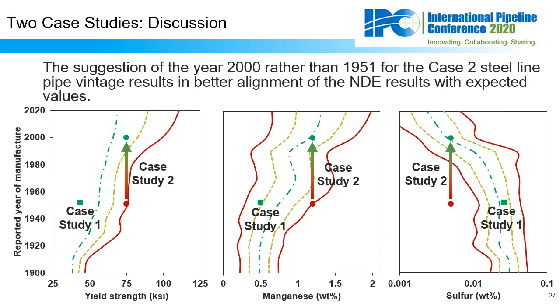And here you see that the suggestion of the year 2000 rather than 1951 for the steel line pipe from case study 2 aligns much better with the historical data. On the left we have yield strength. In the middle we have manganese. And on the right we have sulfur content. And you see that the realignment to the year 2000 brought the data much closer to the mean line and the expectation for that vintage.